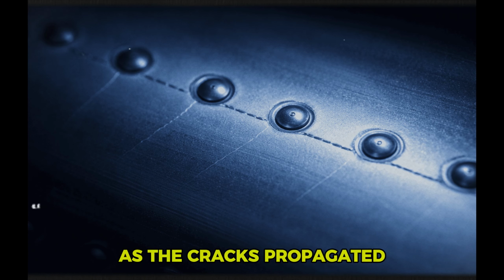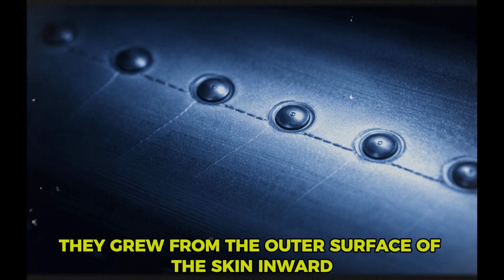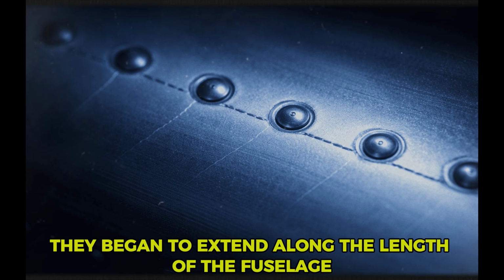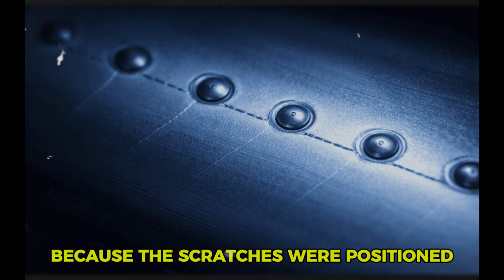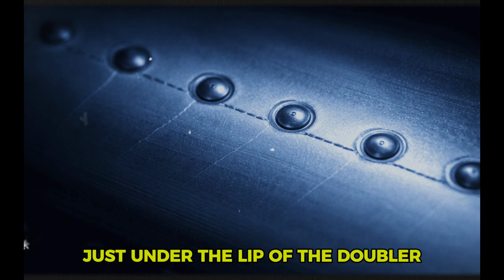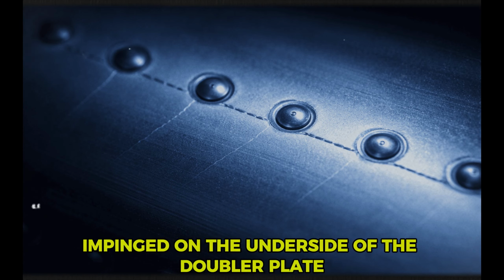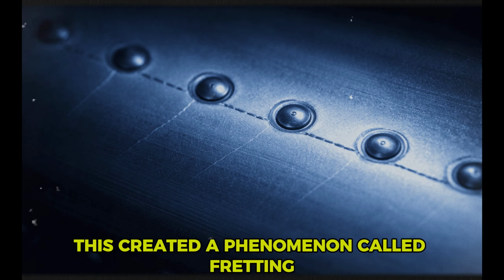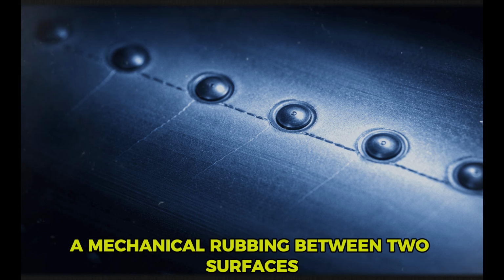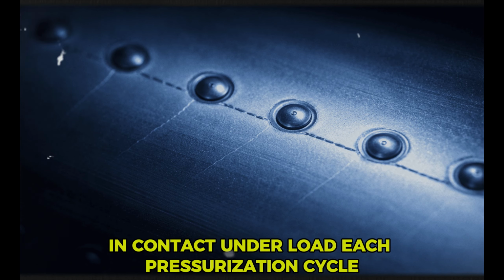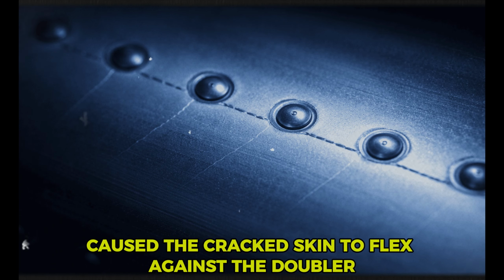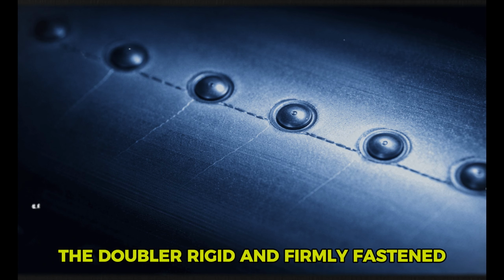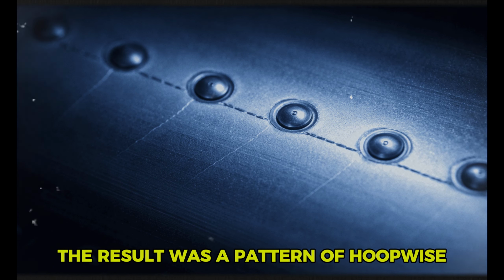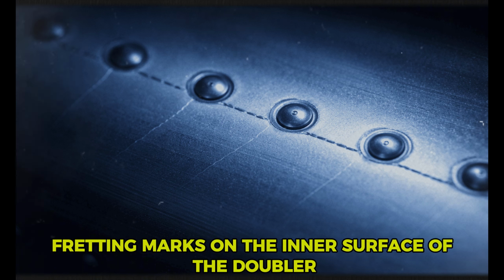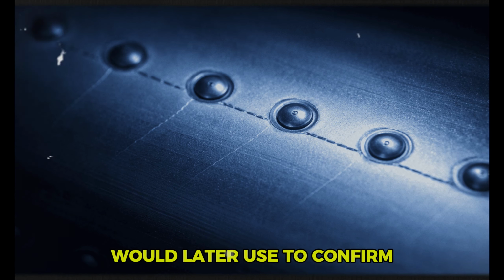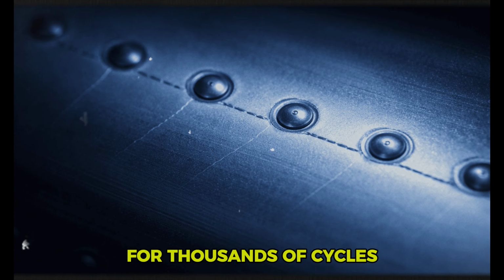As the cracks propagated, they grew from the outer surface of the skin inward, through the thickness of the metal. Then they began to extend along the length of the fuselage. Because the scratches were positioned just under the lip of the doubler, the growing cracks eventually impinged on the underside of the doubler plate. This created a phenomenon called fretting, a mechanical rubbing between two surfaces in contact under load. Each pressurization cycle caused the cracked skin to flex against the doubler. The doubler, rigid and firmly fastened, resisted this movement. The result was a pattern of hoop-wise fretting marks on the inner surface of the doubler, marks that the investigators would later use to confirm that the crack had been moving beneath the plate for thousands of cycles.